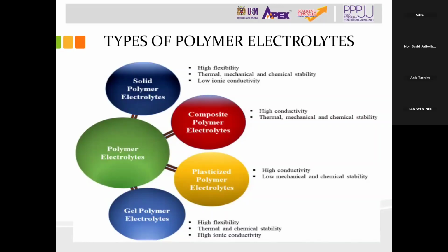For the second type of polymer electrolytes, we have composite polymer electrolytes. In the composite polymer electrolyte, conductivity of the polymer also decreases due to the presence of ion pair formation. This behavior is observed mainly because of the low dielectric constant of the polymer matrix. To overcome this issue, high dielectric constant inorganic fillers such as TiO2 and SiO2 are dispersed into the polymer electrolyte to avoid ion-ion association. The obtained electrolyte combines the properties of the ceramic filler as well as the polymer and will result in a flexible, mechanically stable composite polymer electrolyte.